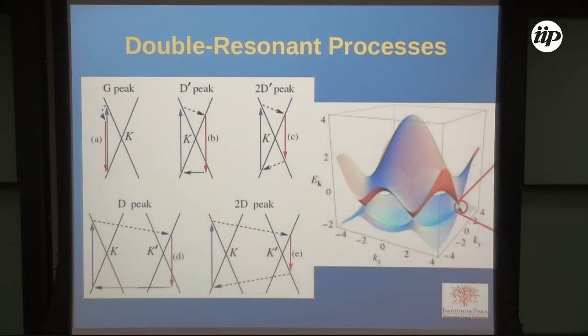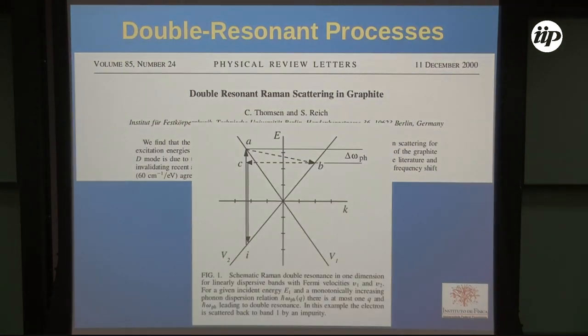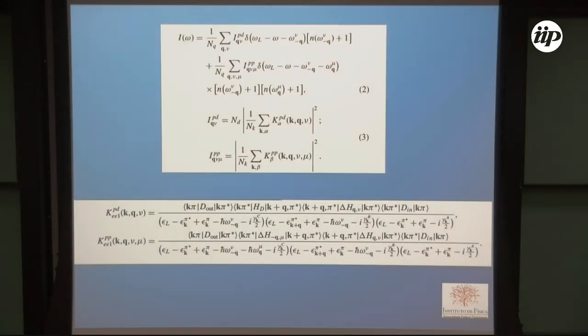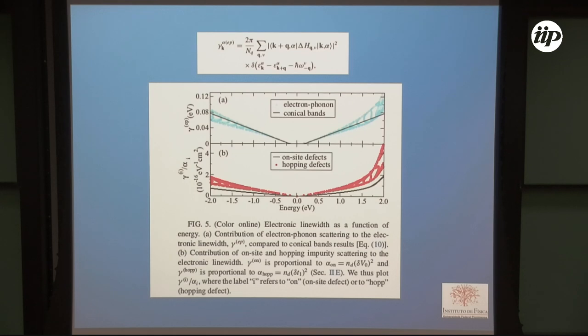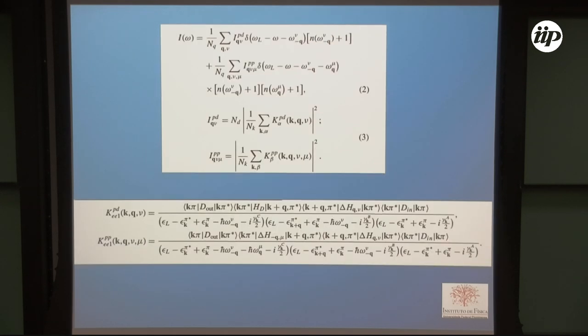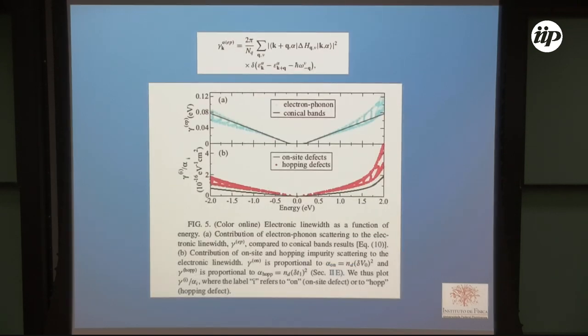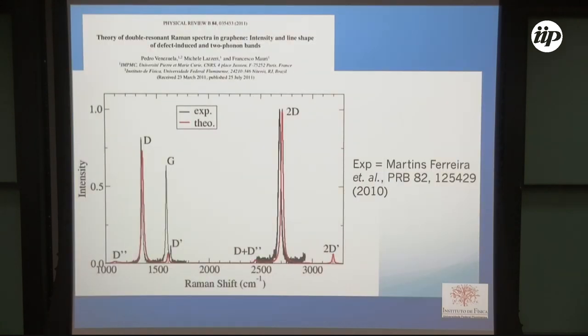So with all this care, we can have a good description of the process. Also, the other thing is that we have here this broadening parameter. This is an energy, and this is related to the inverse of the lifetime of these processes. We calculate it explicitly, considering scattering by electron-phonon or electron-defect operators. And this is also very important to have a good description of this term.